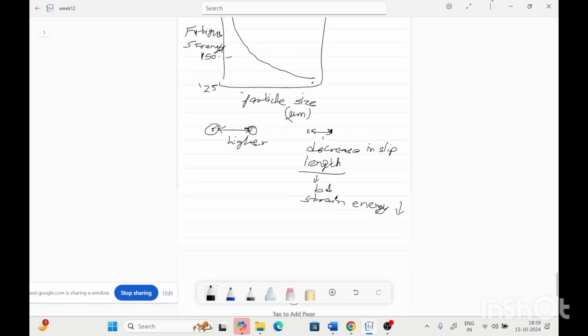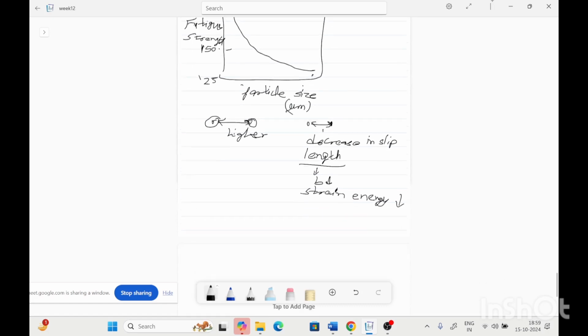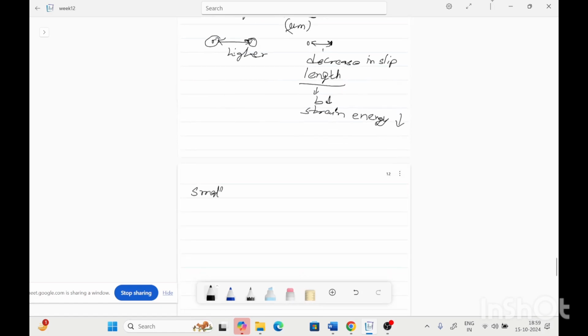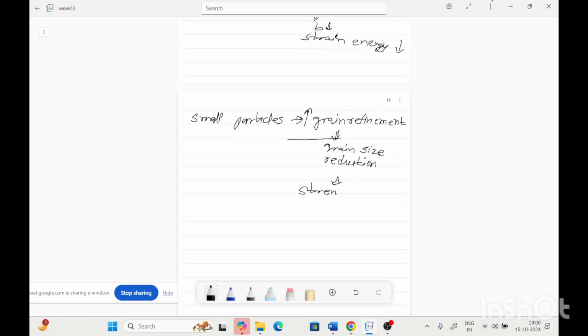And the decrease in particle size also affects the grain refinement. Means for smaller particles, the grain refinement will be higher, so the grain size reduction will lead to strengthening, and due to strengthening, the tensile strength and the fatigue strength both will increase. Will be high.